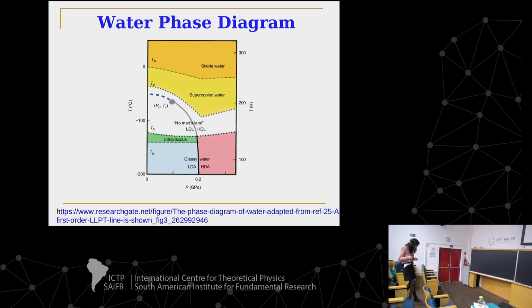The only experiments that you know people are doing is that they do out-of-equilibrium experiments. Okay, so they hit lasers in a little drop of water, and they see that when you hit laser on the thing, you can see two densities. But it doesn't live long enough to be stable, and nobody expects it to be stable because it's in this area in which you don't expect stable water.